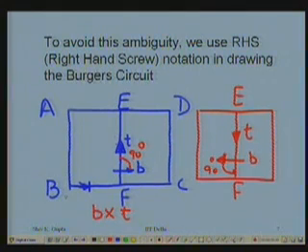Which way does it point? Out of the plane. Out of this plane, but in the crystal, if this plane is the slip plane, which way is it pointing in the crystal? Vertical. The C direction. Above the slip plane ABCD, it points above the slip plane, and that is the side where I have the part plane.